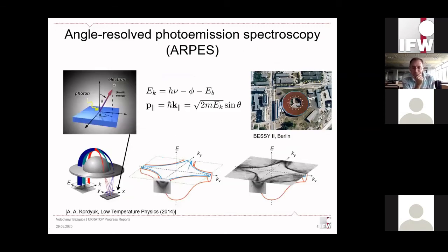So a nice method to study all of these materials is ARPES. I won't go into the details here. I will just say that it allows you to directly see the electronic structure of the material, and it's based on photoemission. Using this method, you can reconstruct the whole Brillouin zone of the material.